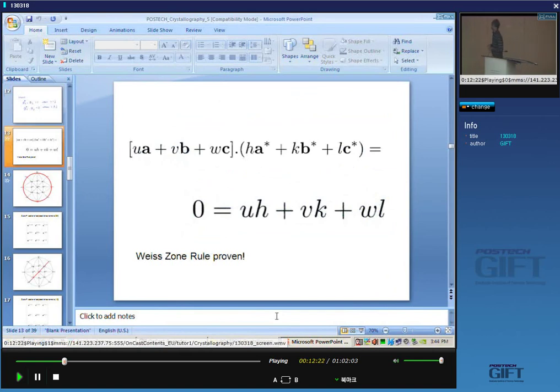Right, so you recall the Weiss zone rule, where if I have a direction u, v, w, and a plane normal h, k, l, if that direction lies in that plane, then this sum will be equal to zero. Okay, so that's the Weiss zone rule. We can now prove that. If I take a dot product between the real space vector u, v, w, and a reciprocal space vector h, k, l, okay? Then what is uA dot hA star? It's uh, right? What's uA dot kB star?